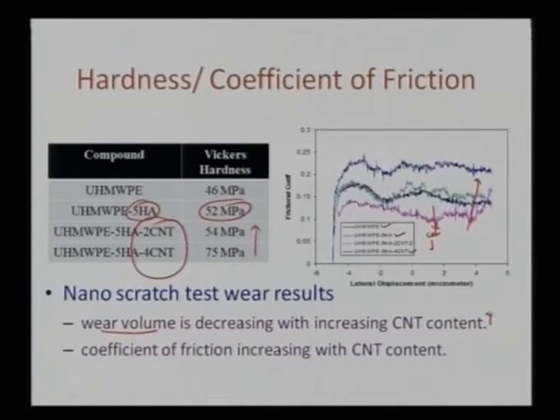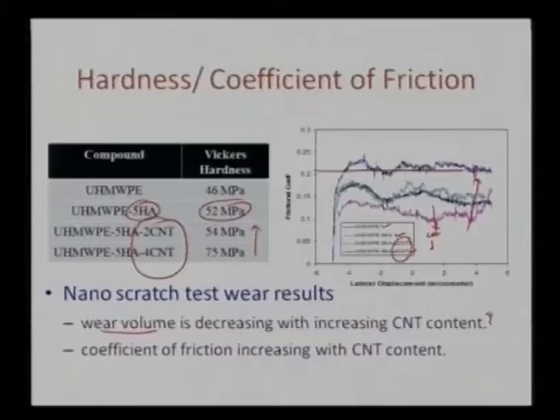Whereas once I am adding some carbon nanotube to it, CNT is introducing much more strength to the polyethylene matrix. They have very superior mechanical properties. So the indenter tip finds it very difficult to displace the material. At nano level, things are very different, and it finds it harder to displace the material. So lateral force goes much higher. That is the reason we can see an increase in the coefficient of friction once we have more CNT content. So it is in agreement with the observed wear resistance, or the wear volume loss, which was observed in the